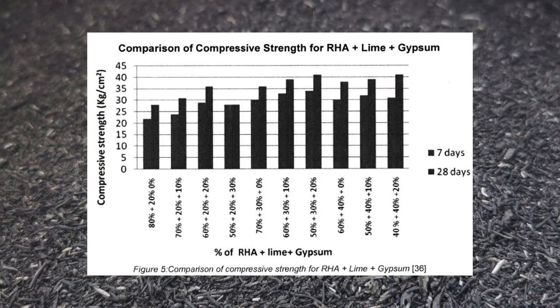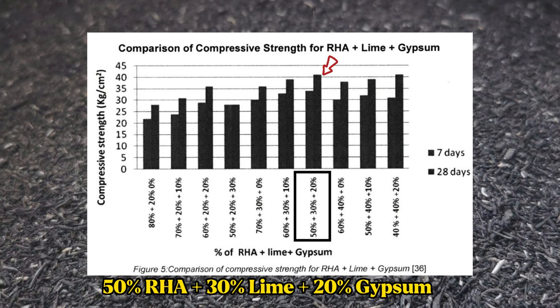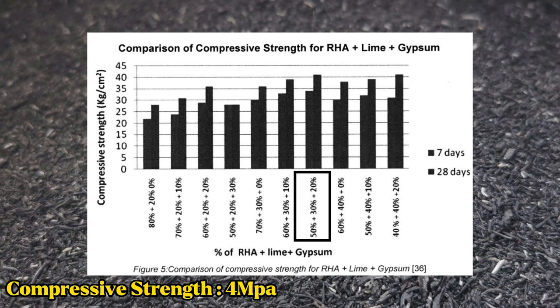In a study conducted, we see that the highest compressive strength using rice husk ash occurs when a brick uses 50% rice husk ash, 30% lime, and 20% gypsum to make brick. The compressive strength at 28 days is around 4 megapascals. The water absorption at this composition is 16.9%, which is less than the 20% as per standards.